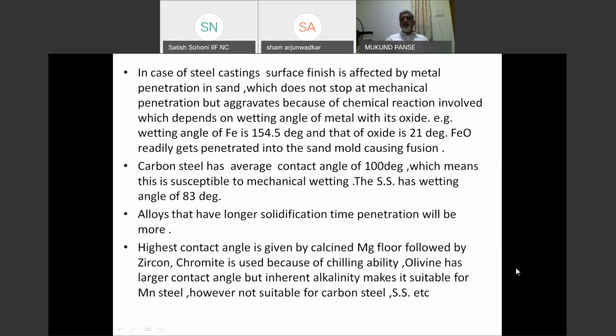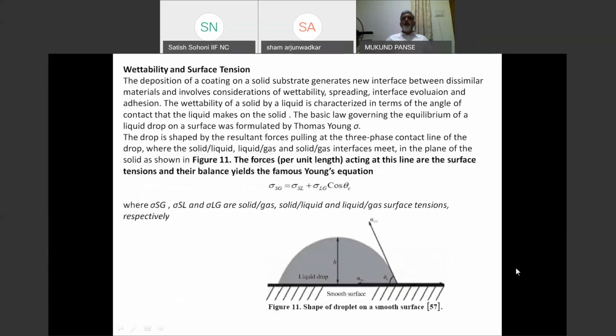This penetration is caused by the wettability, that is, the ability of the metal, that FeO and Fe2SiO4 form, is substantially higher. We'll see what wettability is. If you drop water on glass and if you drop oil on glass, you can see the contact made by the oil and the contact made by the water. Compare it with a steel ball kept on glass. The steel ball will have a minimum contact, oil will have more than that, water will have much more. Now imagine a drop of water on a chalk or sand. It will get spread immediately. This is what wettability is, the surface tension of a liquid when it is coming in contact with a solid layer.